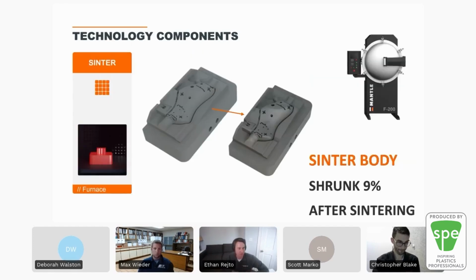After printing is complete, you take this part, which is just now binder and metal powder held together, and you put it into a furnace. If you're familiar with powdered metal or metal injection molding, this is a sintering step. You get just below the melting temperature of the material, and the metal powder actually fuses together.